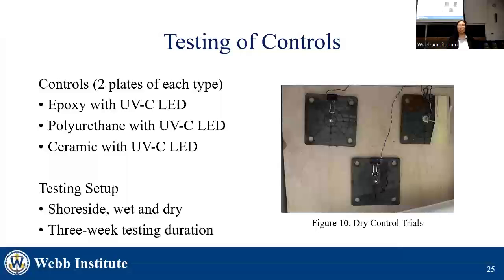In addition to our primary trials, a series of 6 shoreside control plates were set up for continuous monitoring of UV light and coating degradation. These included 2 plates of each epoxy, polyurethane, and ceramic coating arrangements. 1 plate of each coating type was submerged, while the other was left in open air. The open air set may be seen in Figure 10. You may note the tape on the rightmost plate.